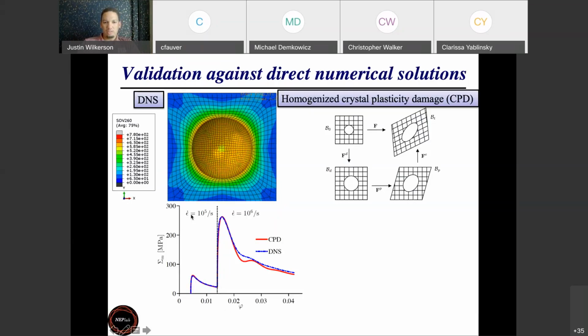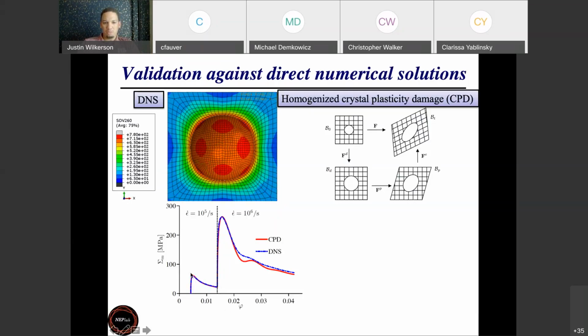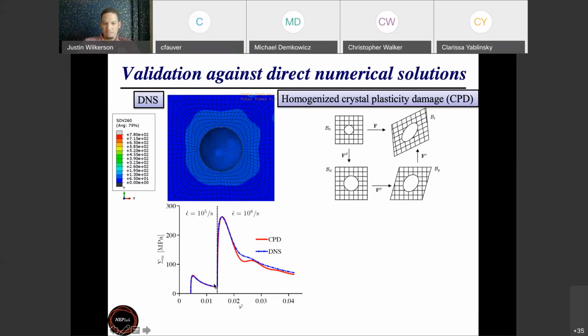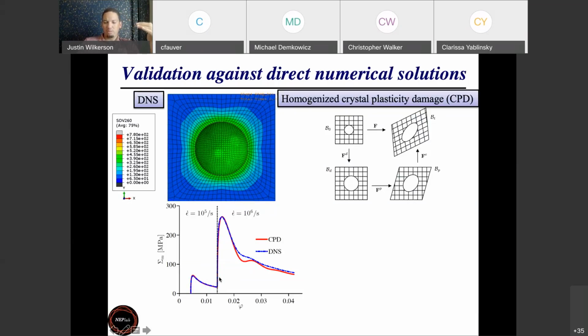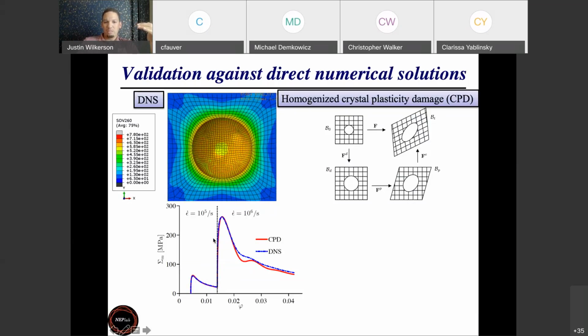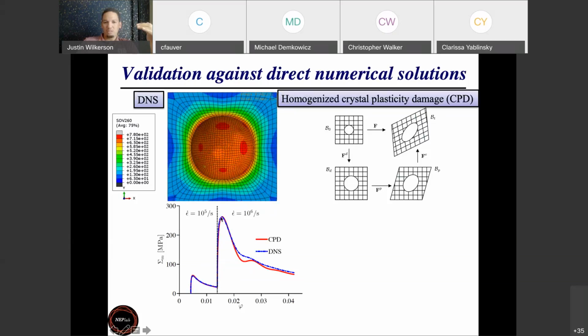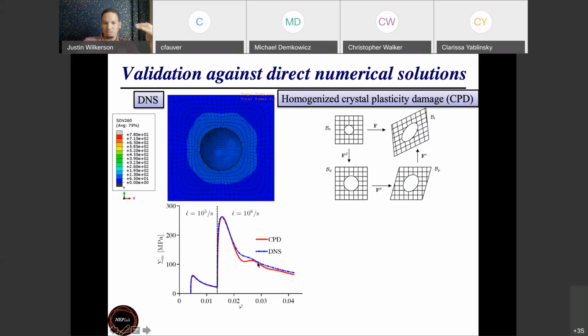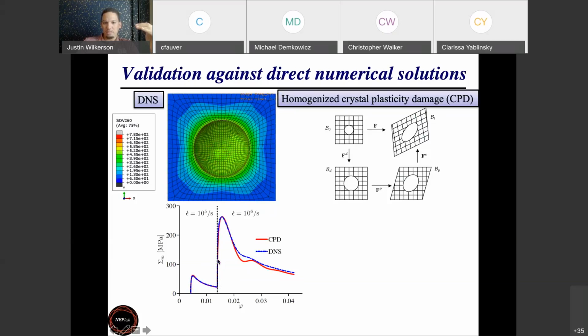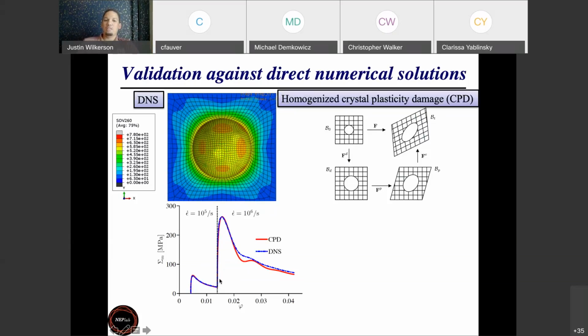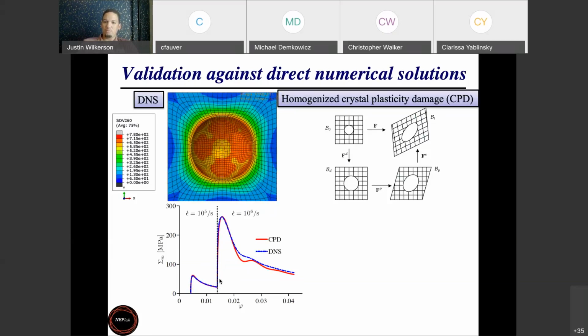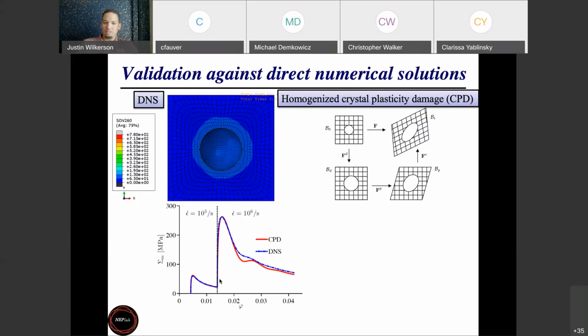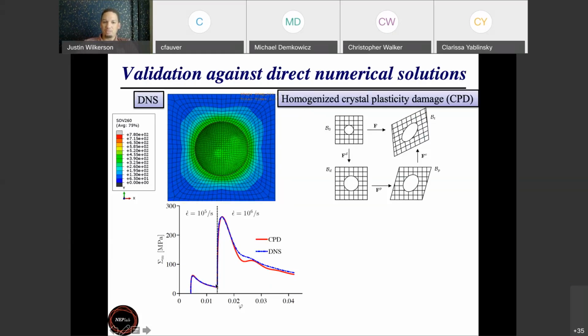So we were moving along at a strain rate of 10 to the 5, come up to this peak, and then come down. And then all of a sudden here, we increase the strain rate by an order of magnitude up to 10 to the 6. And then what you'll see is a jump in the stress. It comes back to a peak, and then it falls down due to relaxation. So this extra stress that we got, that was all a strain rate effect. And it's all coming from this physics-based framework that we've built. So that's the dynamics of the void itself giving you this extra stress.